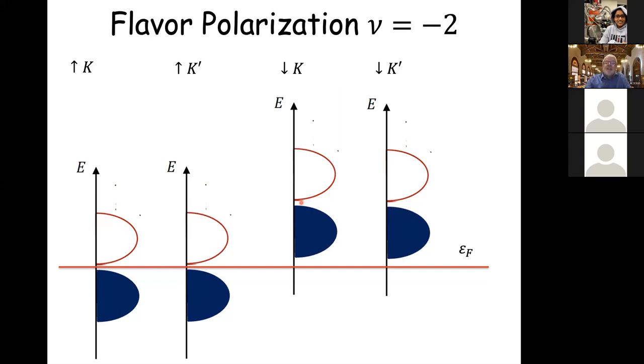And what that does is it gives us the opportunity to break flavor symmetries and create low energy gap states by placing the Fermi level in the gap between the flat bands and the remote bands for some of the four flavors, and in the gap created at neutrality by breaking, it turns out, sublattice symmetry for some of the flavors. So in this case, these are showing the four flavors. This is actually thought to be the insulating state for band filling factor -2, which means 2 holes per Moiré period in twisted bilayer graphene. And so 2 of the 4 flavors are neutral, have occupied valence and empty conduction, and 2 of the 4 flavors have their flat valence band completely emptied in this broken symmetry state.